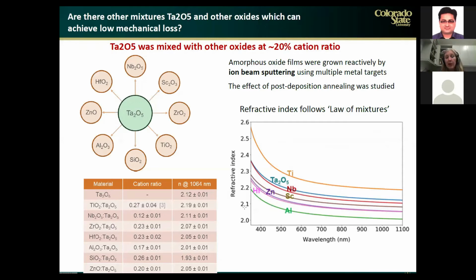So the results that I just showed you were focused on adding titania to tantalum. So we asked ourselves, are there any other mixes that will give us also low mechanical loss? So we carried out a study in which we mixed tantalum pentoxide with other oxides, for example, niobium, hafnium, zinc oxide, alumina, and silicon dioxide, and others. And in all of these samples that we produced, we tried to keep the cation ratio at about 20%. Of course, when we mix materials, then we are also modifying the optical properties.